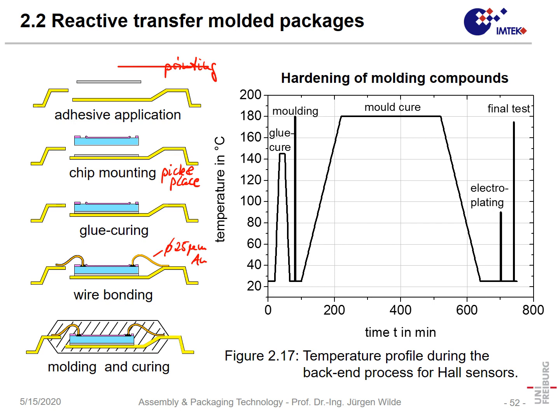It is cooled down, transferred to the post-mold cure oven. Here we keep it for 4 hours. We cool it down slowly. Then we go into electroplating. For instance, the lead frames on the outside must be tin plated in order to be solderable.